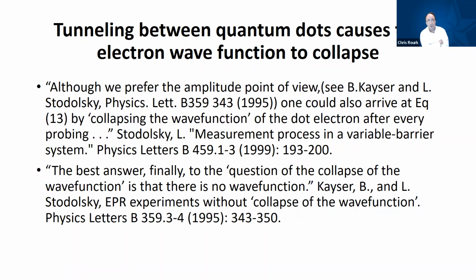Now, quantum dots are different from ferritin. So when you talk about collapsing the wave function at ferritin, the question is, what is it collapsing on? Is it collapsing on iron, Fe3+ iron in the core, presumably? How is that occurring? What happens to the electron after it collapses? Because the Fe3+ iron is in a ferrihydrite crystalline structure, and all of a sudden it becomes Fe2+ iron, is reduced, and it no longer can maintain its structure in the middle of the crystal. And then you have a bunch of other components. So it's a very unusual chemical process going on, and how the electrons can be stored for hours within the core if they bounce around from crystalline structure to get trapped in other configurations. So that would have to be modeled.